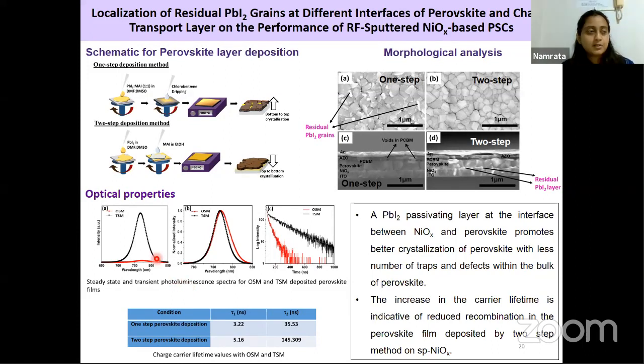Going to the basic principle of photoluminescence, the higher the peak intensity, the more radiative recombinations. So we need more radiative recombinations in the perovskite for the cell to perform well. We want to eliminate non-radiative recombinations, as they act as defect sites, whereas radiative recombinations enhance the performance. So clearly, we can see from the SEM also that the crystallinity for the two-step method increased. That means that defects reduced, and this complements the PL result. With a reduced number of defects, we have a higher PL intensity.